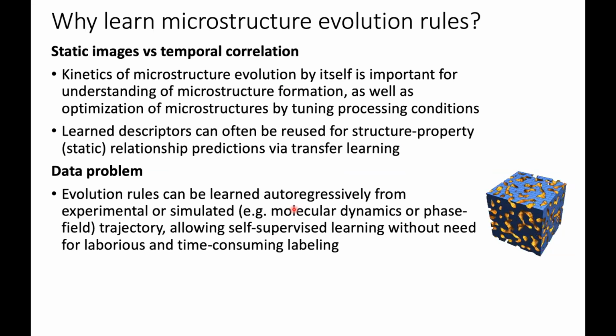Here we care about the temporal correlation because the kinetics of microstructure evolution by itself is very critical for understanding the formation of microstructures, and knowing the kinetics is important if we want to optimize the microstructures by tuning the processing conditions. And additionally, if we learn the microstructure evolution rules through their temporal correlation, the obtained descriptors can often be reused for structure property relationship predictions via transfer learning. So the temporal correlation helps us understand the static images.